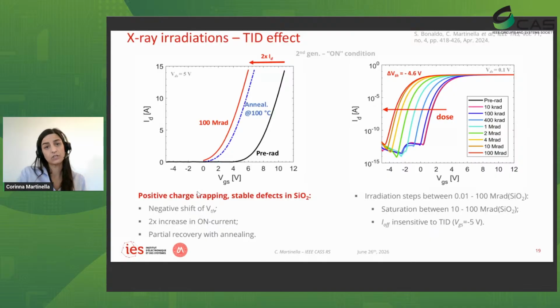What we observed, if we look at this plot, for example, is different transfer characteristics, and we can observe that by increasing the dose, we see a shift of the curve towards the left. So we have a shift of the threshold voltage towards negative values. This was due to the trapping of positive charges in stable defects in the oxide. We saw a little bit of recovery after annealing, but not too much.